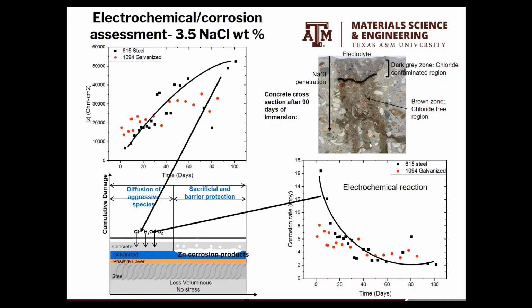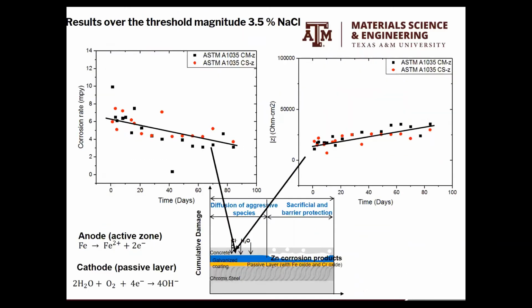Now, based on the modeling, based on the schematic, you see that, for example, if we have the RC system, this is the uptake of the water, all right, of the electrolyte. We use 3.5%, which is way more than the threshold. So with the water penetration, you see that's why the corrosion resistance in terms of the impedance is not very different from steel and galvanized. Why? Because it hasn't reached the rebar yet, all right? That's why you see a similar behavior after 100 days, which means that we are at this stage, the initiation stage, where everything is similar, not equal, sorry. Similar because we have the concrete that is putting up the barrier. Once we pass the concrete, everything is different, all right? So even though we compare to a galvanized system, it is pretty comparable.